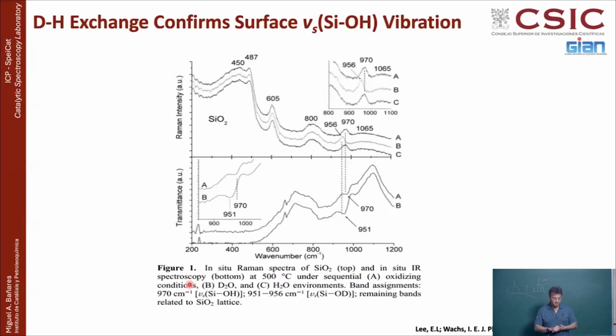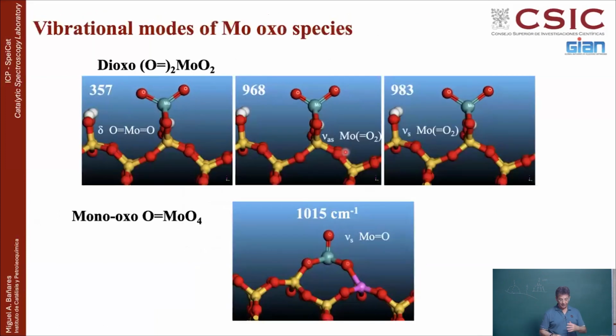Okay. The same thing that you make with oxygen exchange, you can also make with the hydrogen-deuterium exchange. And again, you can see how there is a frequency shift. For instance, here, you can see how this is associated with the hydroxyl group on the surface of the silica, and how the other bands of the silica are not affected. Basically, these vibrations are associated with siloxane bridges of oxygen-silicon rings, and they don't care about replacing hydrogen by deuterium. But this one is associated with surface hydroxyls, and that one changes, because there is OH or OD, and then there is a change, but the other ones are not affected. So these kinds of things can help you either on Raman or in infrared.